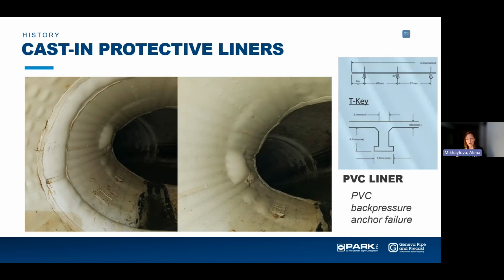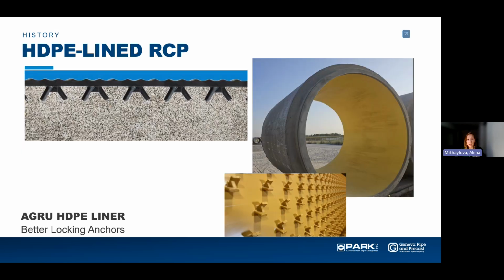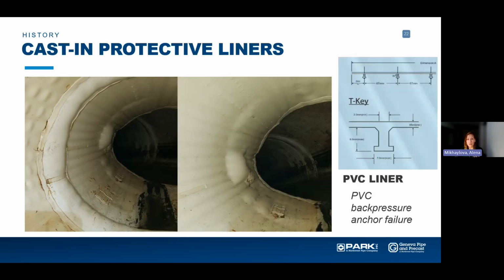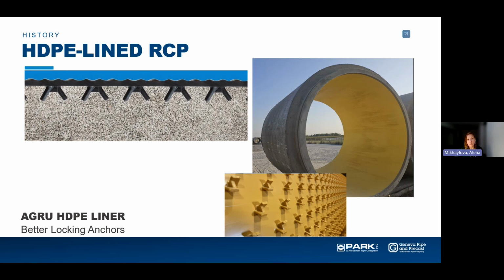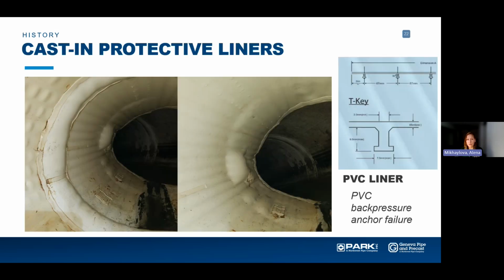And so you may have heard previously, PVC liners were very popular. They started off in the 80s. It was a T-key. It had some design flaws, and the water would build up behind it and pull off some of the anchors. The advantage of the yellow HDPE liner is that it has independent anchors. So in case one anchor pulls out, you have redundancy of the other anchors holding the liner together. HDPE liners are generally thicker, and so they have higher back pressure resistance in case you need it. So let's say you have deep burial and a high water table, you can specify a thicker liner for avoiding bubbling like this.